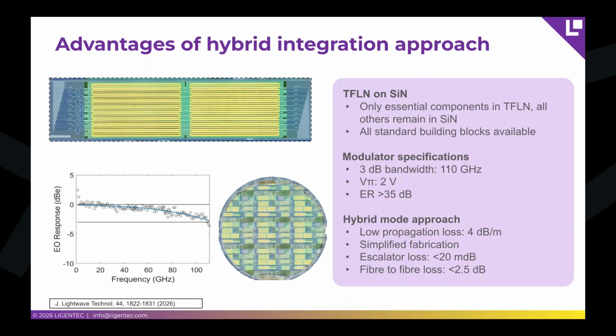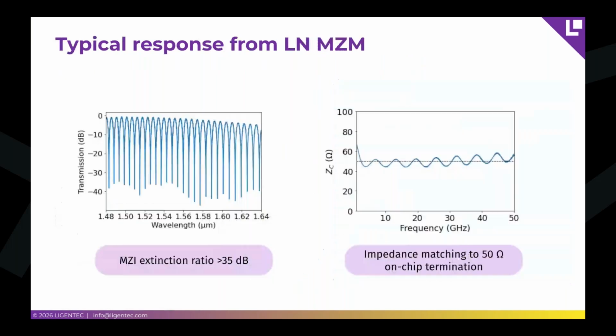That hybrid mode approach gives us the opportunity to have a very low propagation loss, so we can transfer the low propagation loss from nitride into that hybrid mode with a simplified fabrication approach, and have the escalator loss and the fiber to chip coupling not contribute much to the overall losses, so you can get in the end a fully packaged modulator with fiber to fiber losses below 2.5 dB. Also, we have the measurements of the Mach-Zehnder interferometer that clearly show extinction ratios beyond 35 dB, and impedance matching to a 50 ohm on chip termination.